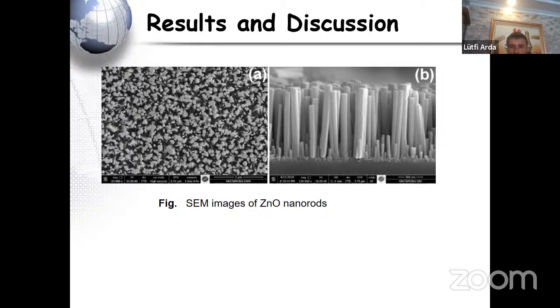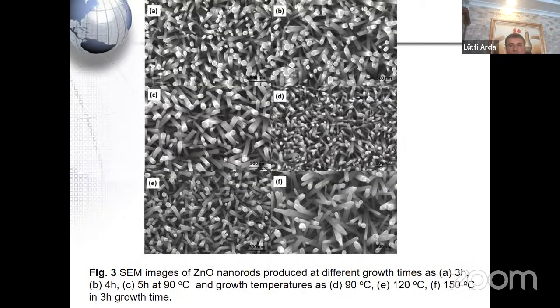Look also at this scanning electron microscope, A, B, C. The figures are for the growth time, and D, E, F are the figures for the growth temperature. All these images reveal that the zinc oxide nanorods are grown perpendicular to the substrate. A perfect hexagonal structure is observed for the nanorods grown at different times, as can be seen in the figures.